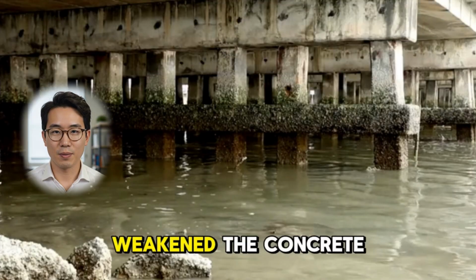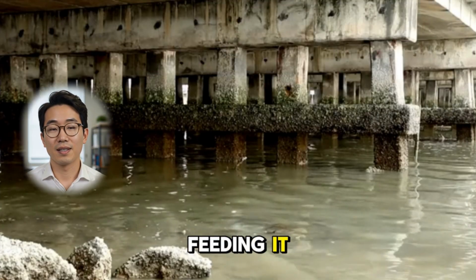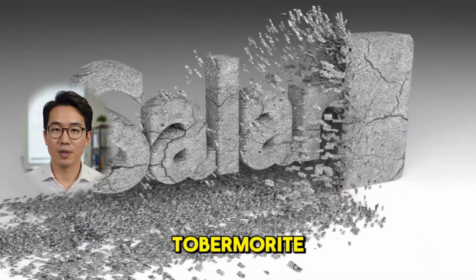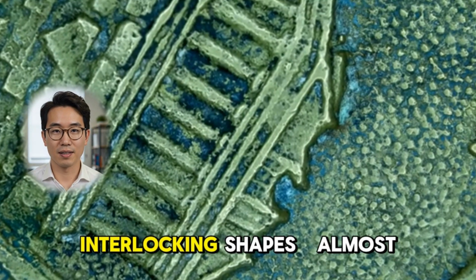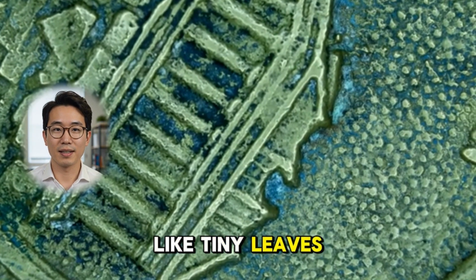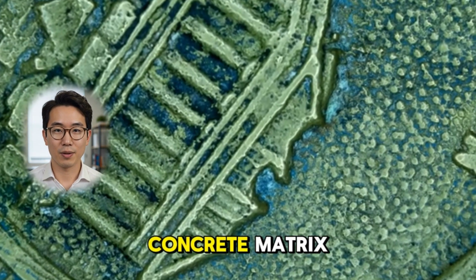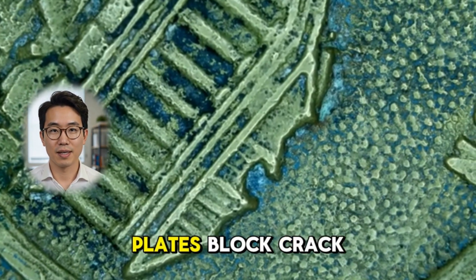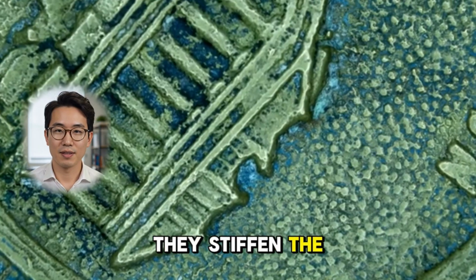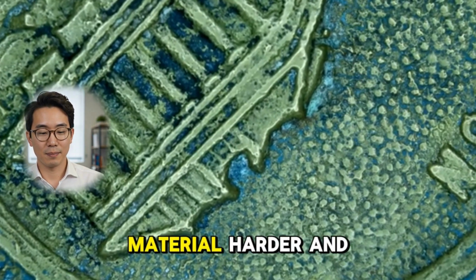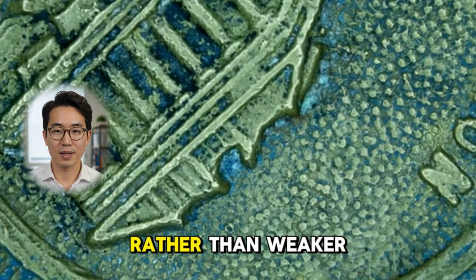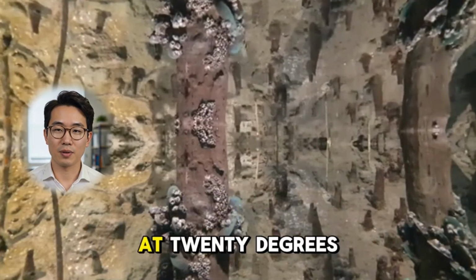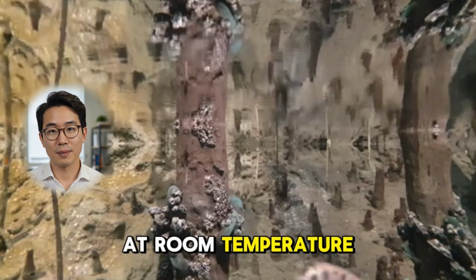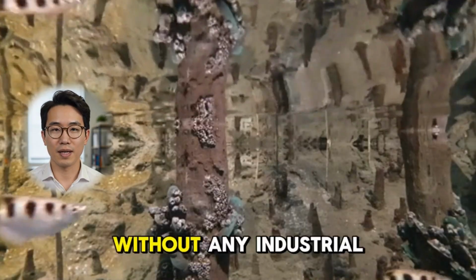The seawater had not weakened the concrete. It had been feeding it. The mineral was called aluminum tobermorite. It grows in plate-like interlocking shapes, almost like tiny leaves stacking on top of each other inside the concrete matrix. Those interlocking plates block crack formation. They stiffen the structure continuously. They make the material harder and denser over time rather than weaker. The Romans were growing this mineral at 20 degrees Celsius, at room temperature, in open seawater, without any industrial process at all.